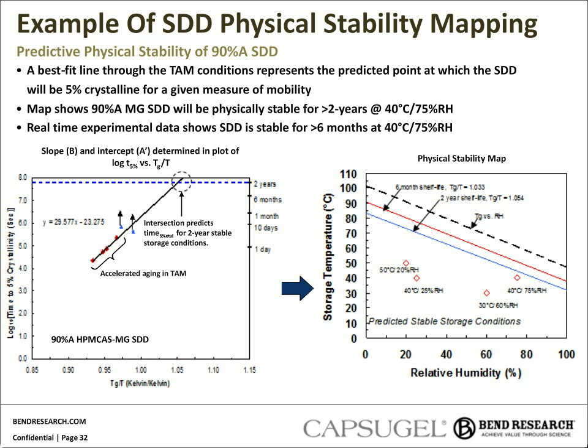And effectively, we'll set up samples at conditions higher than the Tg of the dispersion and watch them crystallize, and then we can put those on this plot and extrapolate out to 2-year stability, so that we can say at a Tg over T condition, in this case of about 1.05, we expect to have 2-year stability. Then we can go back to our storage temperature versus relative humidity map and generate plots where the Tg over T is always 1.05, and therefore generate these iso lines and use this to guide our stability packaging.